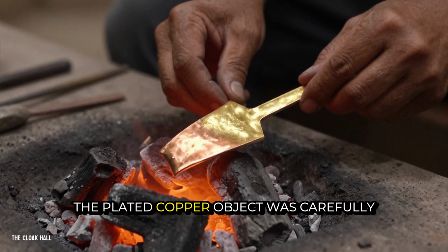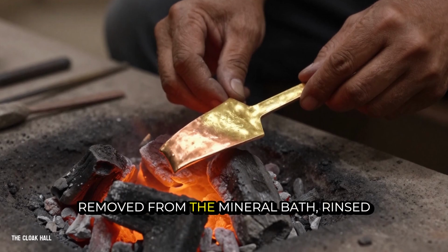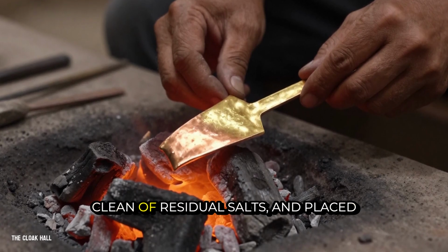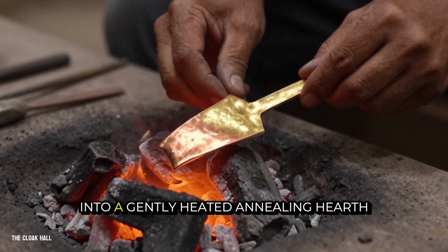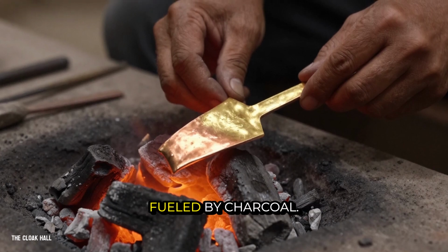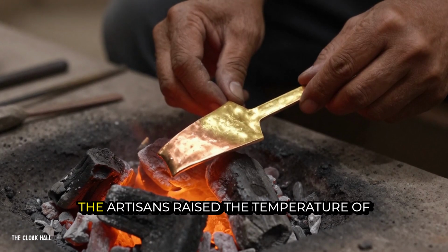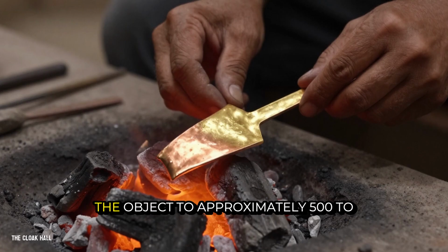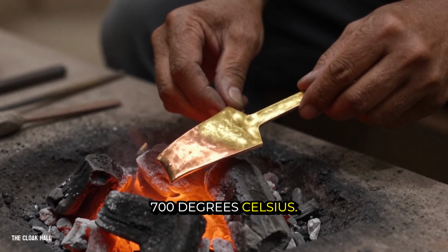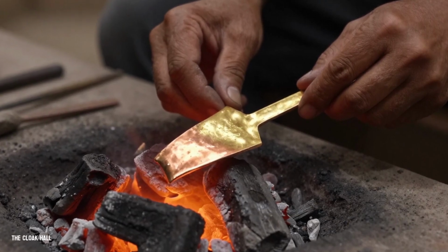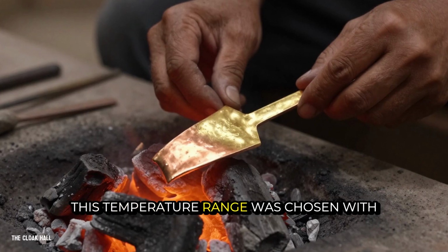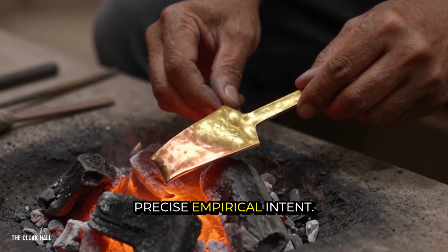The plated copper object was carefully removed from the mineral bath, rinsed clean of residual salts, and placed into a gently heated annealing hearth fueled by charcoal. The artisans raised the temperature of the object to approximately 500 to 700 degrees Celsius. This temperature range was chosen with precise empirical intent.